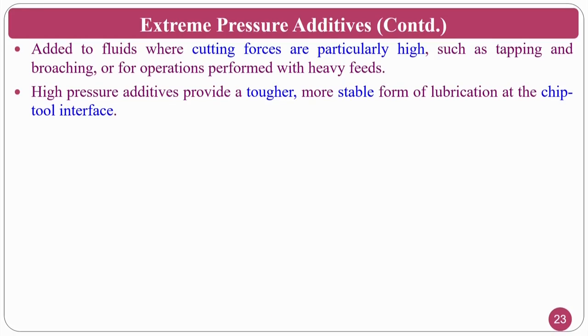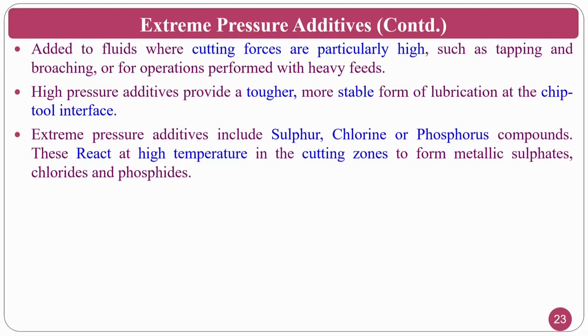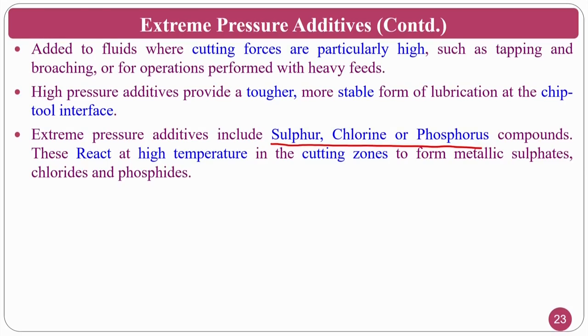High pressure additives provide a tougher, more stable form of lubrication at the chip tool interface. That means it will form a stable soft layer continuously as long as the cutting fluid falls in that area. Extreme pressure additives include sulfur, chlorine and phosphorus compounds. These react at a high temperature in the cutting zone to form metallic sulfates, chlorides and phosphides. What will happen? These compounds react in the machining region where the temperature is very high and form metallic sulfates, metallic chlorides and metallic phosphates. This will give the soft layer.